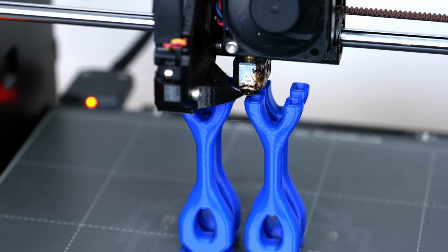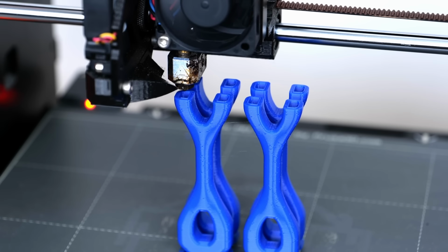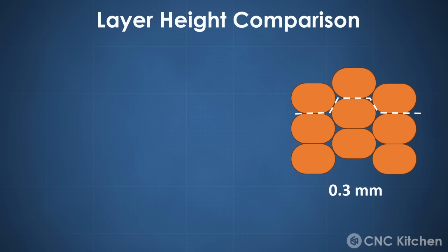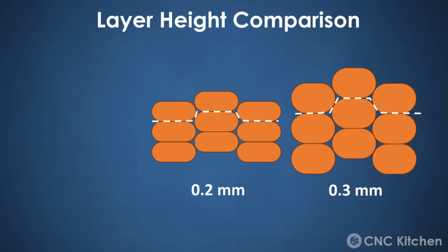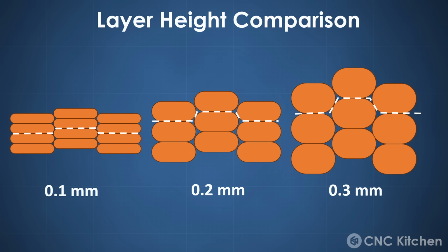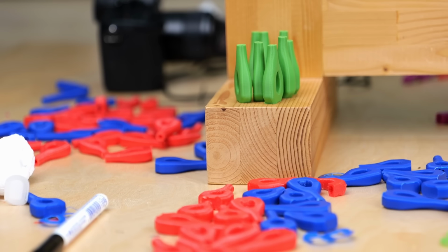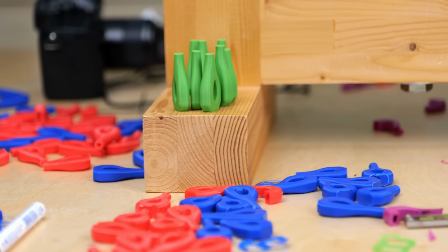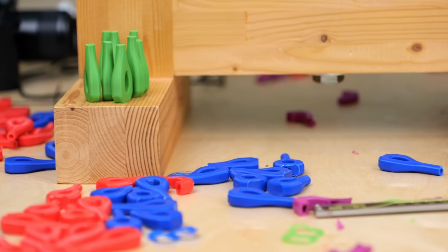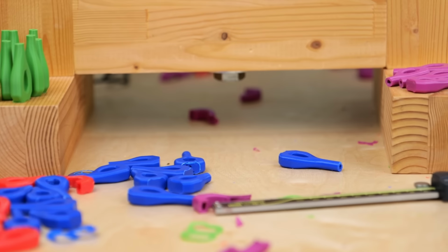One thing I realized during the implementation of this method was that it probably works the best if the layers are rather tall. The thinner the layers get, the less of an interleaving effect we get. I had planned to investigate that further, but the samples that I printed at 0.2 and 0.3 mm layer heights were inconsistent, probably because I used old, wet and unreliable filament.